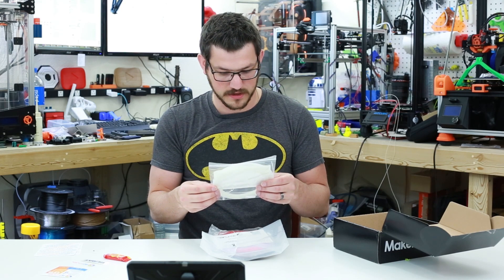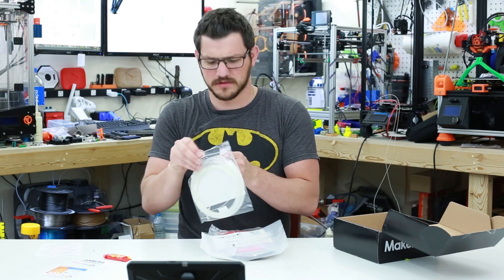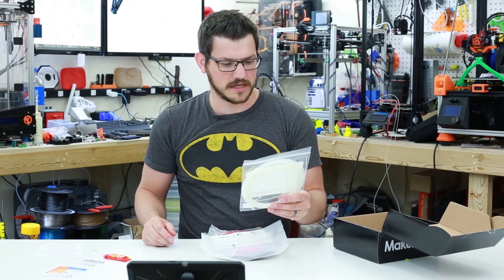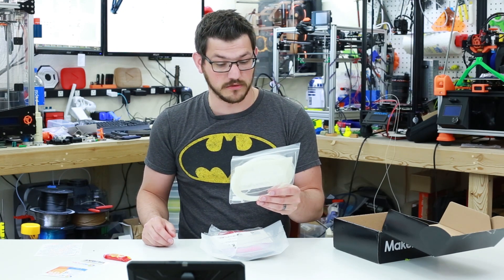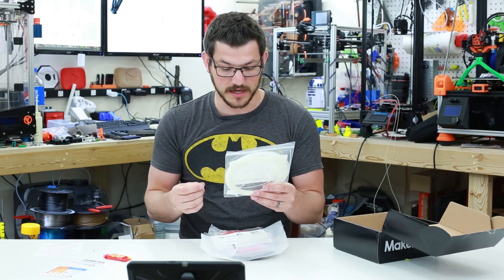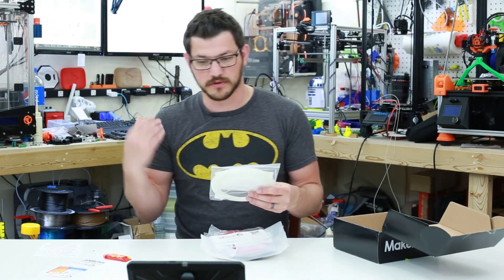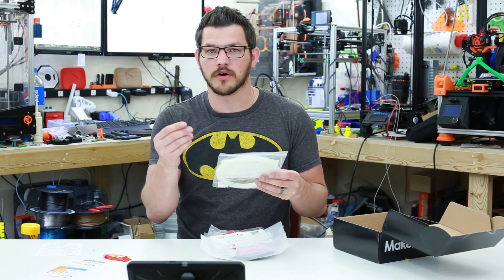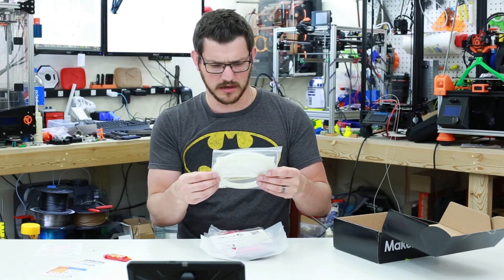First up, we have a glass-filled fiber nylon from Fiber Force Italy in clear — it looks really rough, there's definitely some texture to it. Print settings: hot end 240–260°C, bed room temperature to 70°C plus a glue stick, speed 30–70mm/s. It's a nylon reinforced with fiberglass to improve stiffness while still maintaining toughness. A hard nozzle is advised, and it can be dried with a food dehydrator. I've been drying filament in one for a while. It's translucent right now — I'm curious what the final texture and clarity will look like after printing.